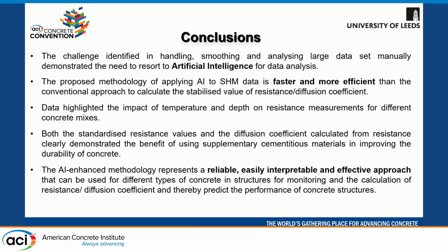Therefore, the conclusions derived from the analysis are, first, that the challenge identified in handling, smoothing, and analyzing large data sets manually demonstrated that there is a need to resort to artificial intelligence for data analysis. Second, this proposed methodology is faster and more efficient than the conventional approach. Third, the data highlighted that there is an effect of temperature and depth on resistance measurements for different concrete mixes. Fourth, this also demonstrated the benefit of using supplementary cementitious materials in improving the durability of concrete. Finally, this AI-enhanced SHM methodology represents a reliable, easily interpretable, and effective approach that can be used for different types of concrete and structures for monitoring and calculation of resistance and diffusion coefficient to predict the performance of concrete and structures.